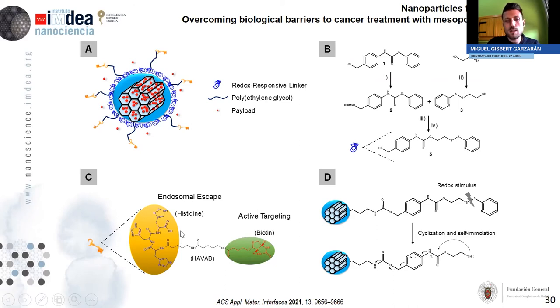This molecule is a multifunctional molecule that has two parts. One is this one, composed of histidines, which is an amino acid known to induce the endosomal escape within the cells. And then we have this part, which is a biotin molecule, which is a targeting moiety because there are some cancer cells that overexpress the biotin receptors. The interesting thing about this is that we can tune on demand this part of the molecule. So for instance, we could use folic acid because the folic acid receptor is also overexpressed in cancer cells, or we could use peptides. It's quite versatile.